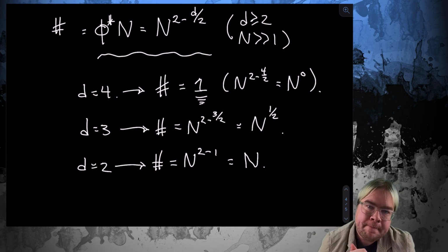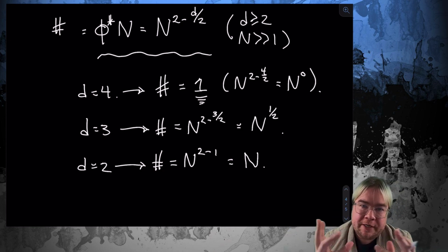All right. So if monomers are interacting with each other, then it's more likely that these real chain effects, the interactions, are going to cause Rg to deviate from the ideal chain models, from the freely jointed chain model. Fair enough. So in d equals 4 dimensions, that doesn't happen. The chain is always ideal.